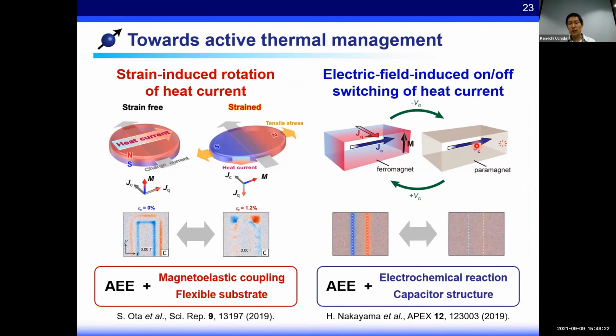In this case, actually, we modulate the Curie temperature of the cobalt film by the electric field effect. Sorry, I didn't show any sample information here, but this sample is a bit special. So due to the redox reaction induced by the electric field, the Curie temperature of the cobalt film is drastically changed. So under the electric field application condition, this becomes paramagnet at room temperature. So the Nernst effect completely disappears.